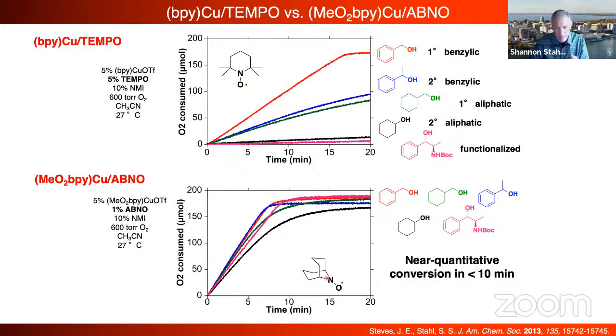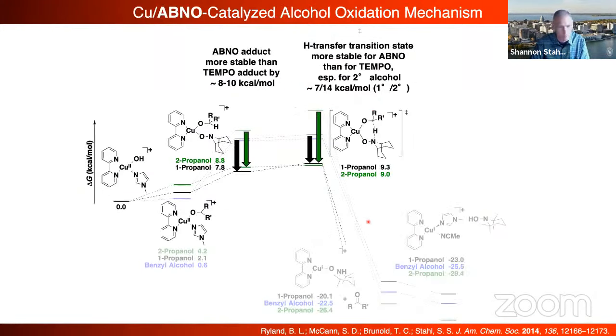And so what you find is this ABNO works remarkably well with all manner of substrates. What you see here is the chemoselectivity, especially well with primary alcohols. These secondary alcohols are essentially unreactive. And so that's essentially showing that, whereas this ABNO without steric effects now oxidizes everything very well. This is manifested in the DFT calculations, which basically show secondary and primary no longer have a preference. In fact, there might even be a slight electronic preference for the green secondary alcohol if you believe those differences, which I think you shouldn't. But the point is that there's very much not a steric effect going on here anymore with this sterically unhindered nitroxyl. Okay.